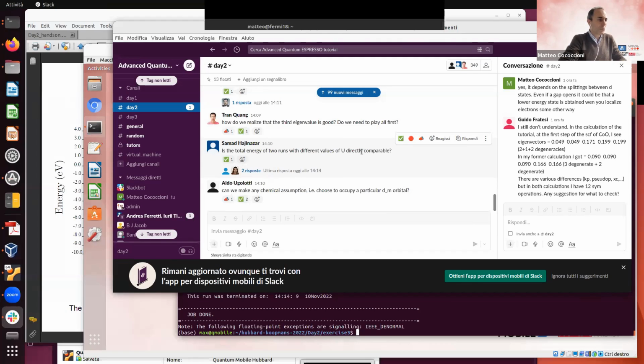Typically when you run with finite U, the system develops a wealth of local minima in the energy, which are different from one another. If you have a good method to push the system into different minima, then you can compare them. It's not always easy. The code doesn't always like the suggestion you make through the starting NS eigenvalue. So it takes a little bit of practice to realize which state you are occupying, which state the system likes to be occupied, and so forth.